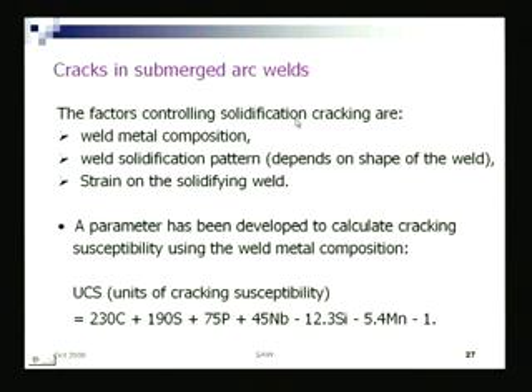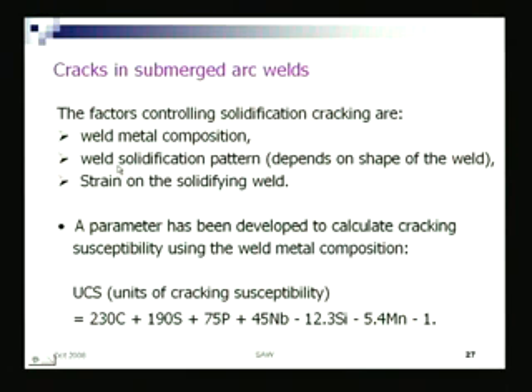By solidification cracking, we mean this: the metal gets solidified, the welding is progressing, and you find it has cracked at the back after solidification. This depends on weld metal composition, weld solidification pattern—that is, what microstructure is forming inside—and the strain on the solidifying weld, what kind of thermal stresses are forming.